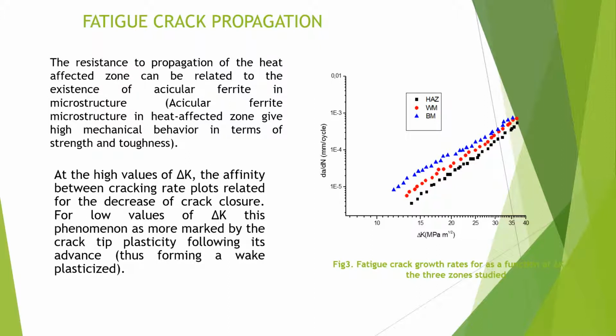The resistance to propagation of the heat-affected zone can be related to the existence of acicular ferrite in the microstructure. Acicular ferrite microstructure in the heat-affected zone gives high mechanical behavior in terms of strength and toughness. At high values of delta K, the convergence between cracking rate plots is related to the decrease of crack closure. For low values of delta K, this phenomenon is more marked by the crack tip plasticity following its advance,